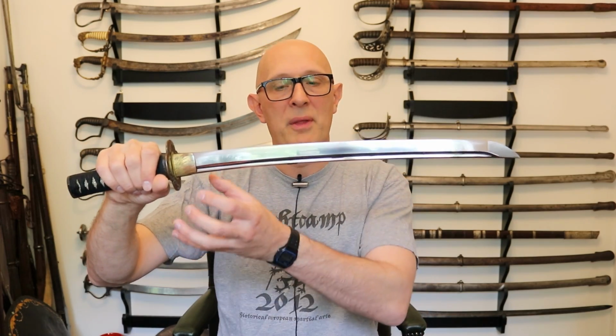So now let's fly back to Japan, and they took a completely different approach and a completely different blade design. They go for very thick blades, very thick spine, with not as much distal taper or taper as we go along the blade. In other words, they don't get very, very thin like European swords do. So they're very thick, but they retain, because of the way they're quenched, they're edge quenched, which produces the famous wavy line of the hamon. So you've got a very hard edge, water quenched incidentally. Water quenching has a very high failure rate, but also can produce a harder edge because the cooling rate is higher. So it can produce a very hard edge that is supported by a softer back.